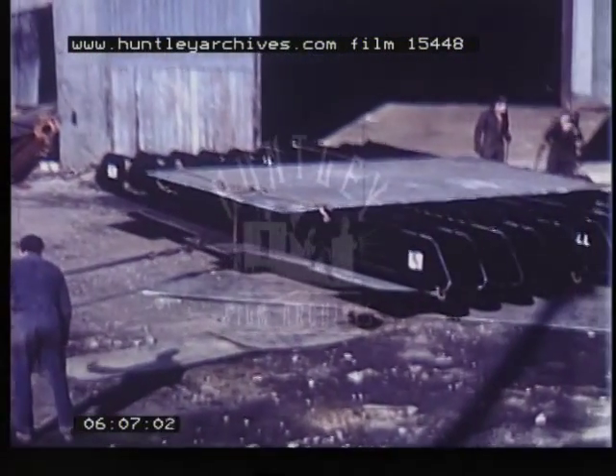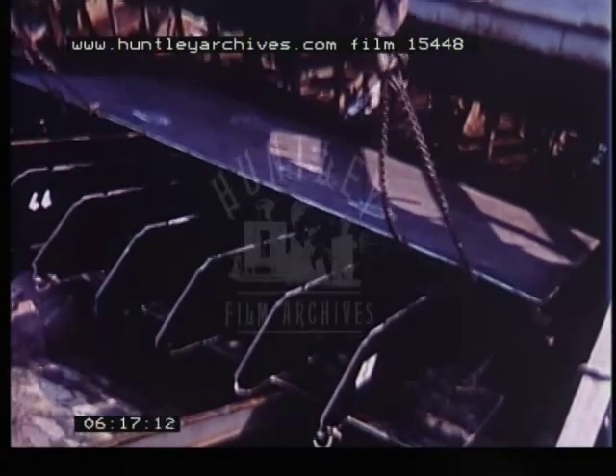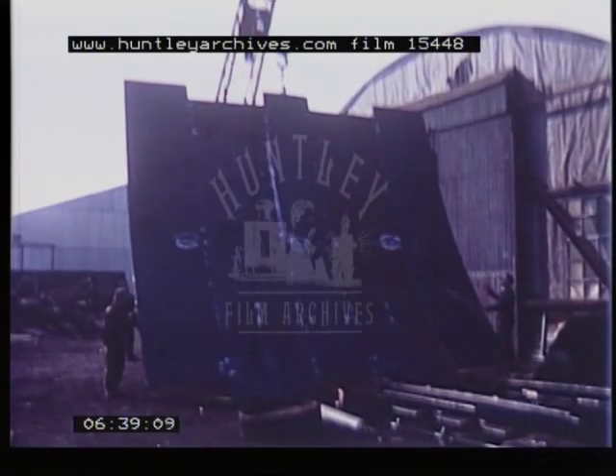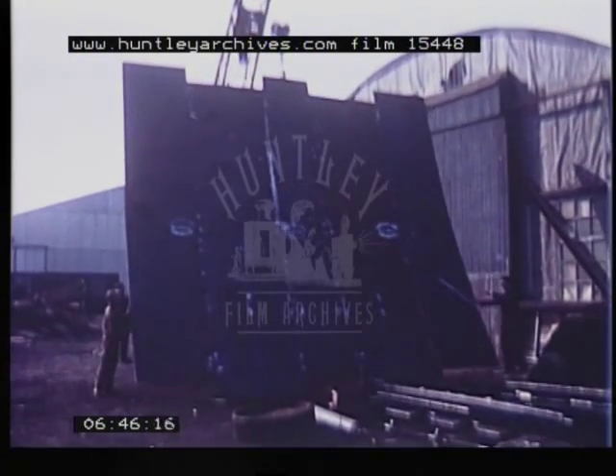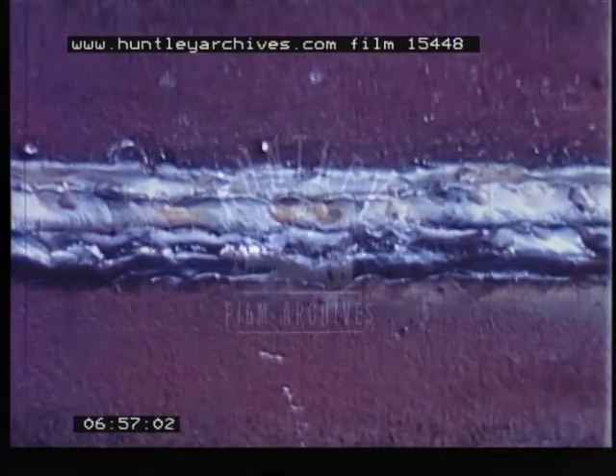Sections of double bottom of approximately six tons were then lowered down the dock side and positioned under the ship to be lifted up and matched to existing plating. This plating had to be double-side welded and large sections were turned over for cleaning out for second-side welding. The degree of penetration with CO2 welding was found in every instance to be more than adequate.